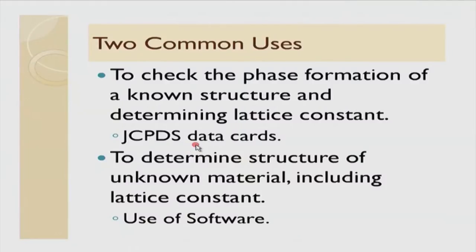For all standard materials, there is something which is called JCPDS data. These are cards which are now available in the form of software. You can have these particular cards and you can match your theta values and find out whether your structure really resembles one of the standard structures for any of the materials.